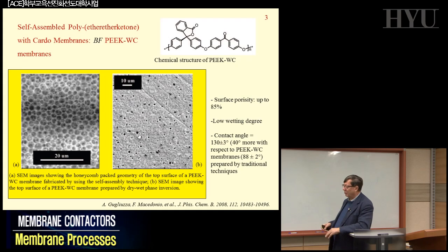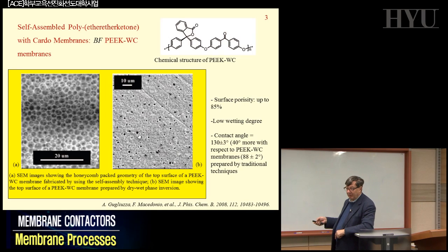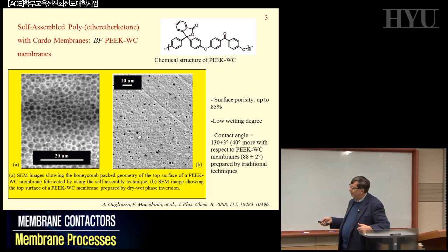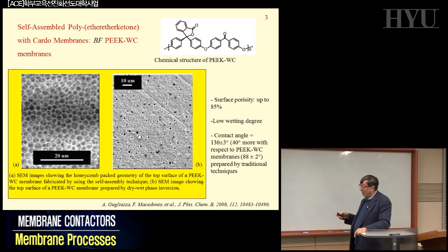Just the conditions that you create give you condensation of droplets all equal, which means that each one of those was a water droplet. After you remove the water, what is left is all the pores equal, because they were formed by a kind of template, the droplet condensation. Quite interesting, because now if this is water, it is one size at a certain temperature.